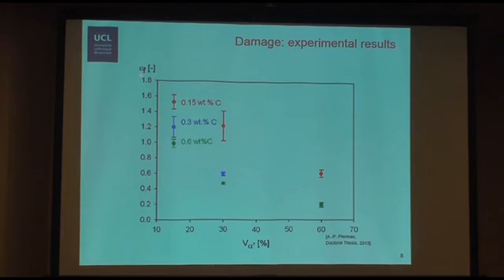Here are experimental results for damage. It's the graph of the fracture strain epsilon f as a function of martensite volume fraction, and it shows the trend that the fracture strain decreases with a higher martensite volume fraction, and also with a higher martensite carbon content. Those trends are already captured by the cellular automata model, but I didn't put the results because it's not quantitative yet. The model runs since recently, so I'm working on it. I don't have results for orientation and morphology yet, but it will be for soon. I just wanted to show the methodology, the approach that we follow for taking into account the different heterogeneities.